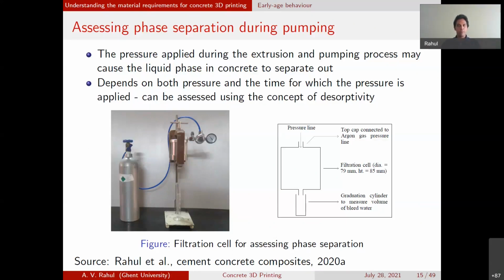If you're using a piston pump, the concrete is pumped by having all the concrete placed in a large piston, and then the piston is slowly moved to cause the concrete to flow through the pipe. But all the concrete placed inside the piston is being pressurized for a very long time, because the piston is very long and it's moving at a very slow rate. Applying this pressure for a long time creates too much water drainage and can leave an unextrudable mass in the piston.